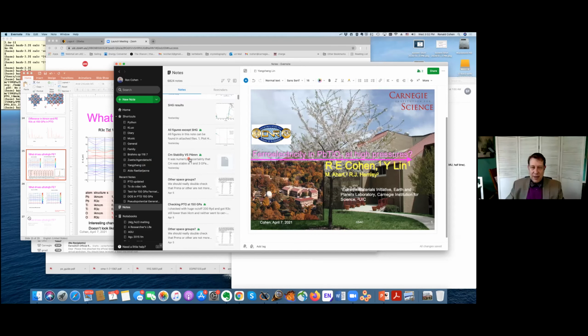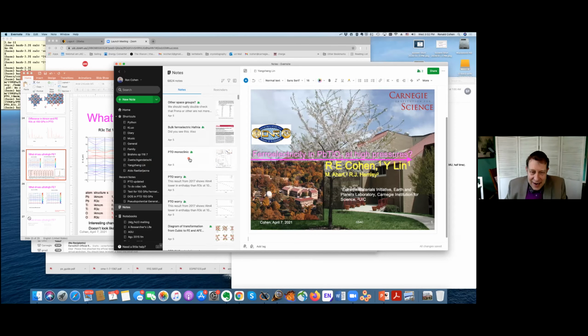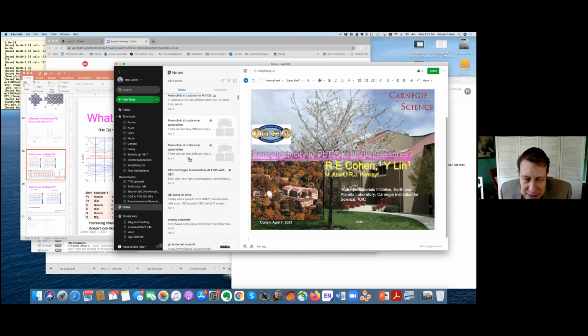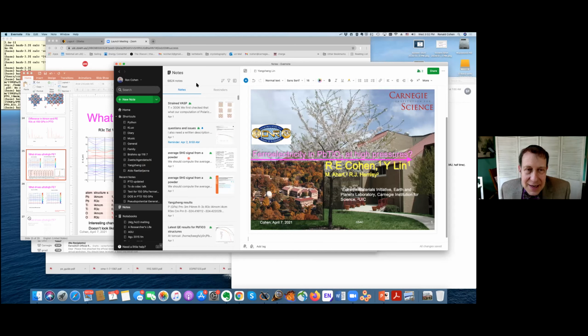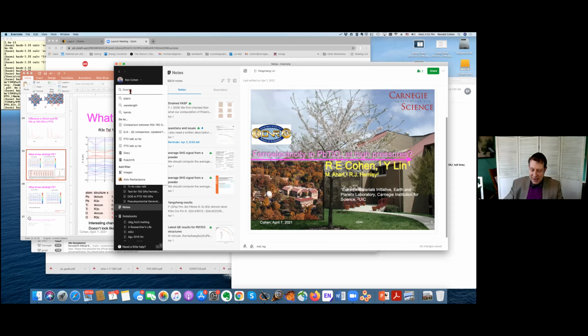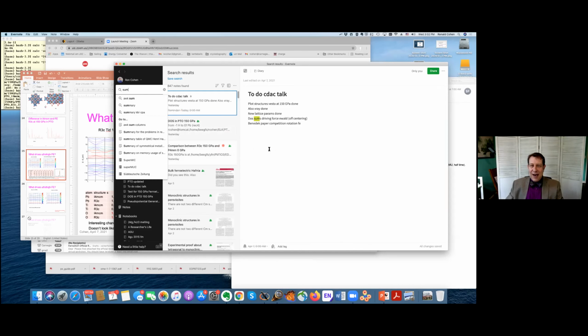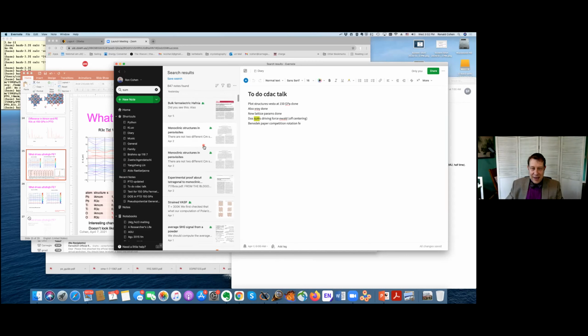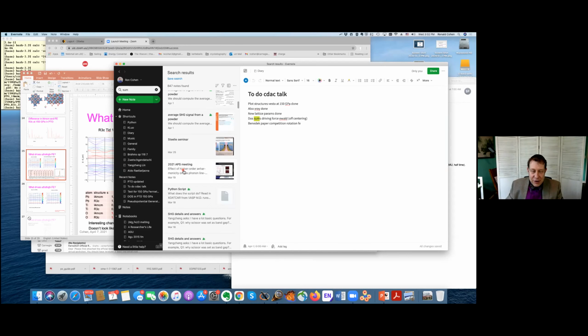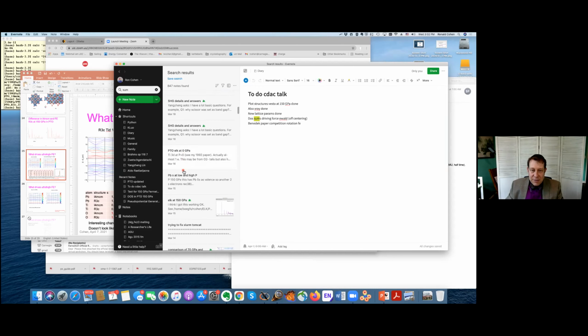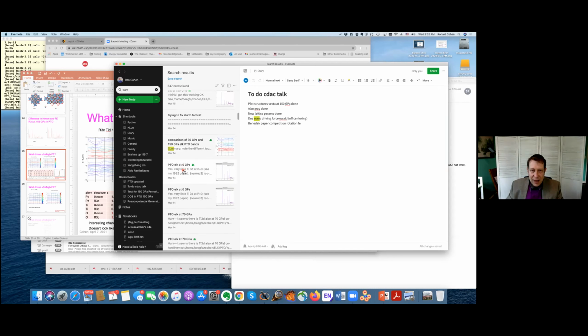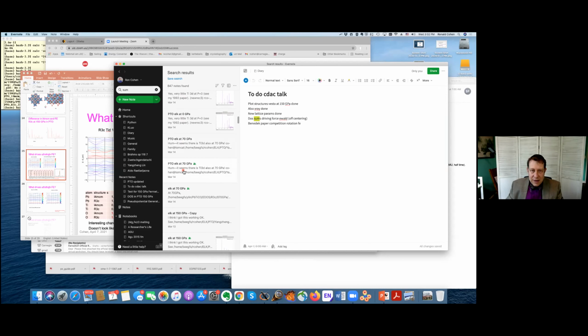Right, let me show something because I actually was looking first for the effects of pressure on this structure. And I was very surprised, I didn't put it in the talk, but surprisingly, you don't see it. So comparing zero pressure and 150 GPa, there's very little change, there's no like S to D or anything like this going on. Let me see if I can find it.